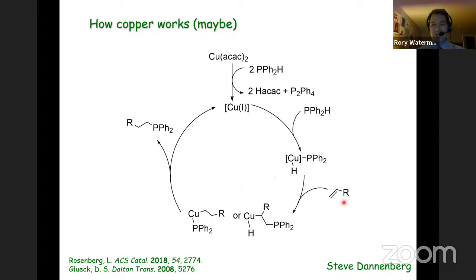This is the insertion-based reaction. This is essentially the required reaction we need to activate the unactivated alkene substrates. The reason I mentioned before the possibility of having differential mechanisms is that the copper phosphido simply is activated as a nucleophile and can attack an electrophilic unsaturated substrate. And that's why we see the difference, and that's why we see acceleration with the electron withdrawing substrates. And so we're not fully there on mechanism. This is a work in progress, but I think it is consistent with the data that we have, and it is certainly a good starting point for us to continue to understand this catalysis, which is itself remarkable.